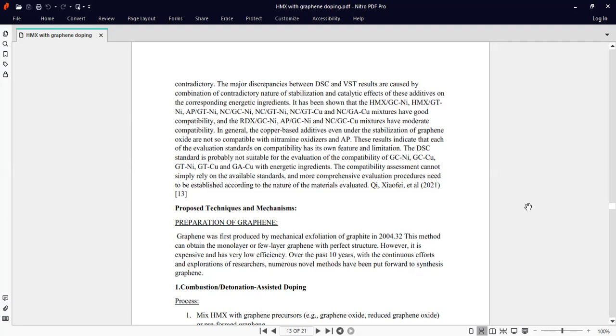The DSC standard is probably not suitable for the evaluation of compatibility of GC nickel, GC copper, GT nickel, GT copper, and GA copper with energetic ingredients. The compatibility assessment cannot simply rely on the available standards, and more comprehensive evaluation procedures need to be established according to the nature of the material evaluated.